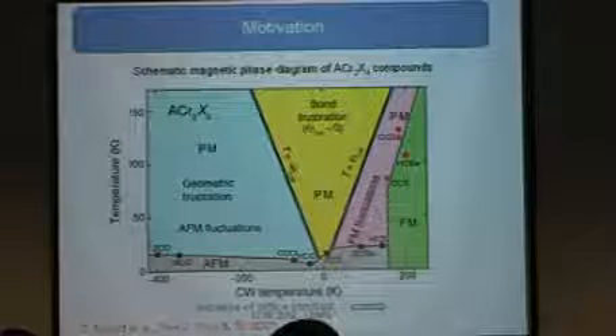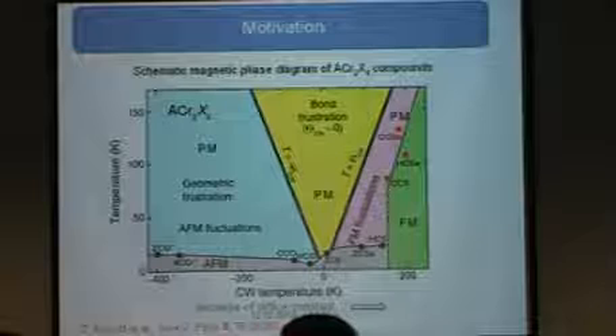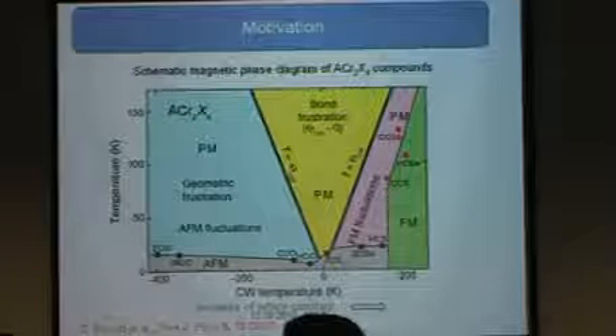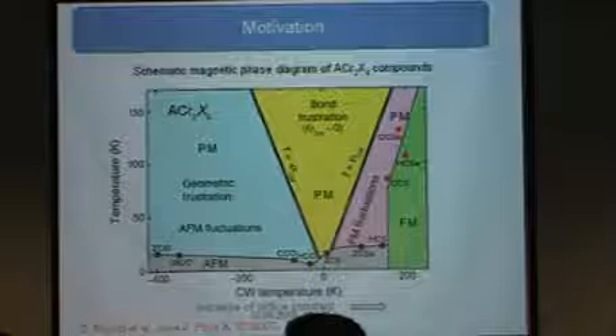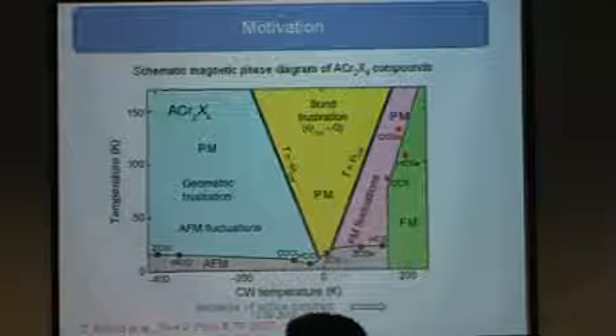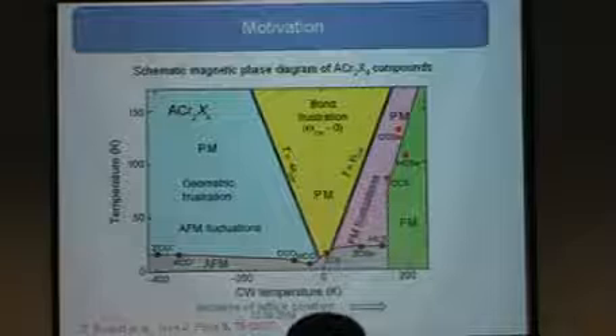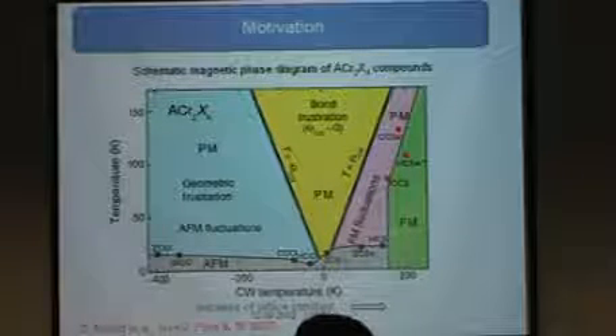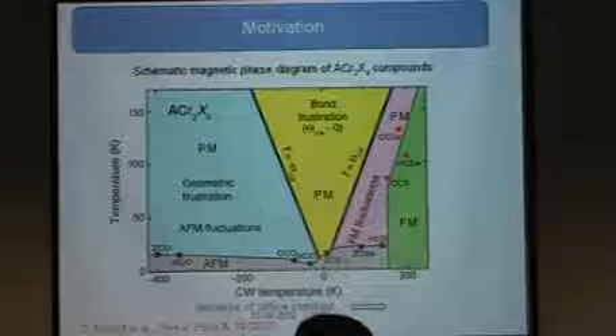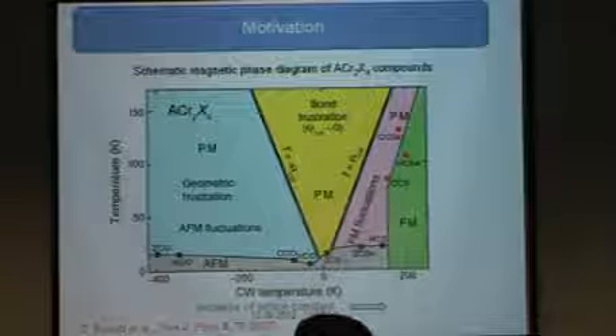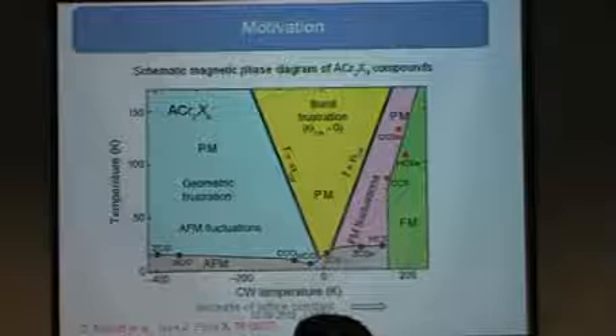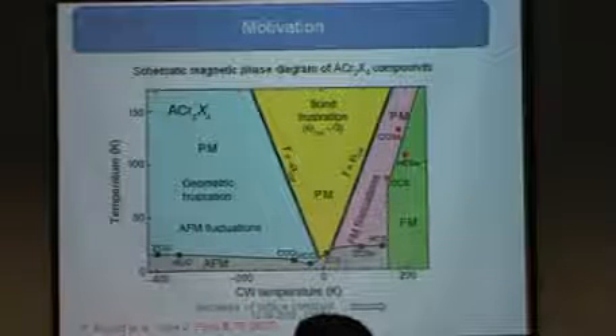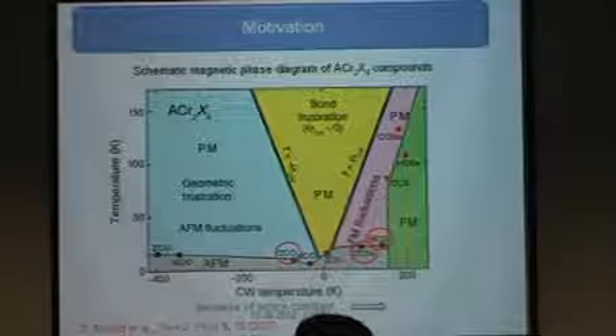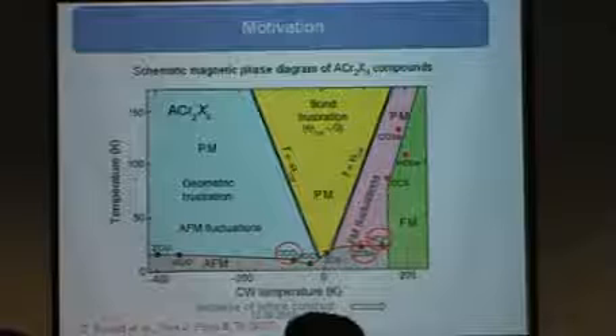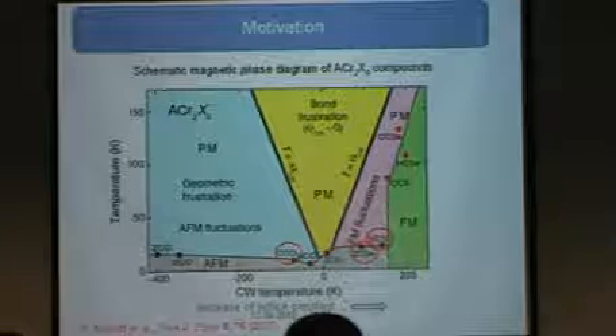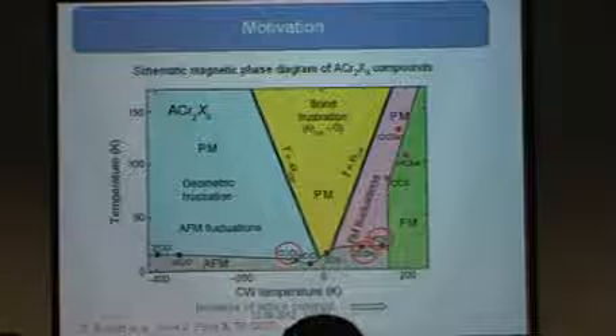So the idea was to stay above this critical temperature where all the systems go to antiferromagnetic, and take one compound from ferromagnetic and apply pressure, then you can reach the antiferromagnetic states. For this reason, we had a preliminary room temperature measurement for these three compounds: mercury chromium sulfide, which is more towards ferromagnetic, zinc chromium selenide, and another, antiferromagnetic cadmium chromium oxide.